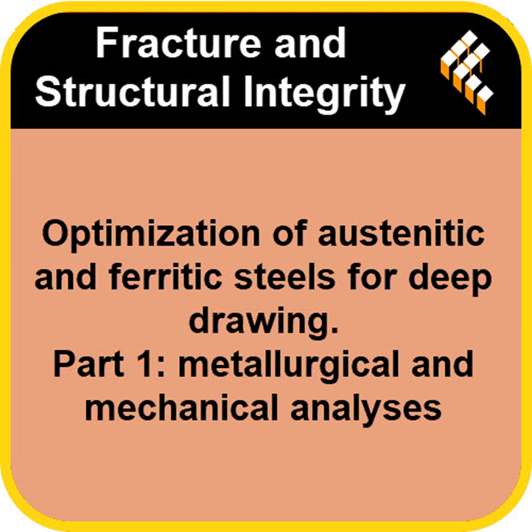This means it resists thinning more when you pull it in certain directions. And that's actually really beneficial for the drawing part of deep drawing, where the flange of the metal is being pulled inwards towards the die cavity. But the Erichsen test is mostly stretching, pushing the dome out. Exactly. So that Erichsen test doesn't fully leverage the ferritic steel's drawing advantage. The isotropic austenitic steel, with its overall superior stretchiness, still wins the stretching contest.